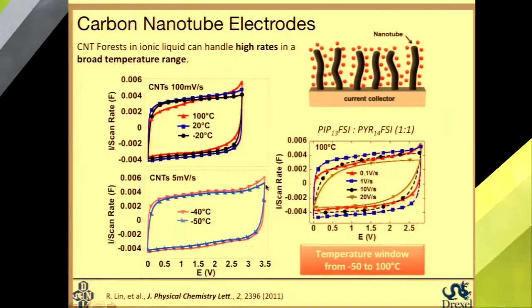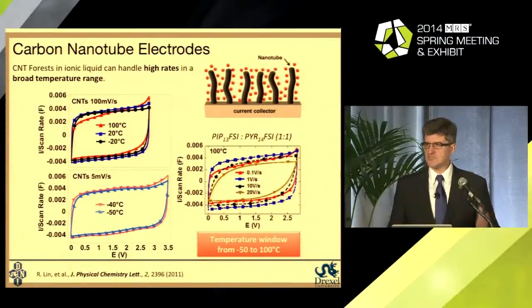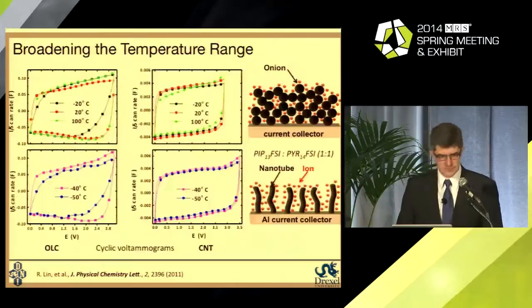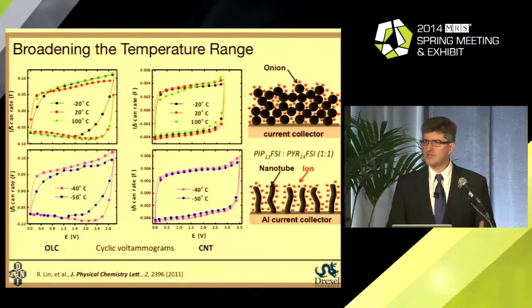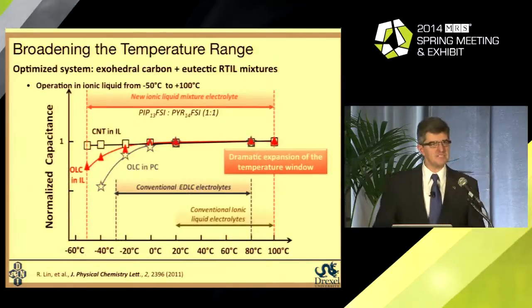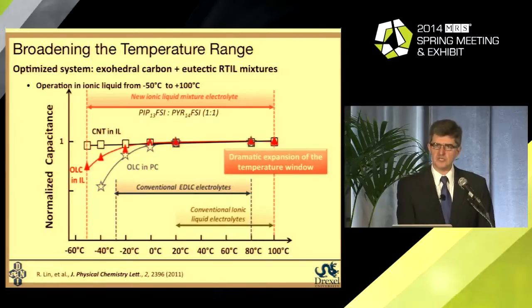But we still can charge it at -50 degrees C, keeping the same nice rectangular perfect capacitive performance. So before this work, there was really no single paper showing that ionic liquid electrolyte can be used below room temperature at all. And here, simply by designing the carbon electrode, we can push it down to -50 degrees C. And you can do exactly the same thing on carbon onions or graphene electrodes. So as a result, by designing with carbon, by understanding how to match carbon electrode materials and electrolyte, we will be able to expand the temperature range from -50 to 100 degrees C for electrical energy storage application. So if you have this as a battery in your car, you will be able to start your car in Alaskan winter or Arizona summer, and you will be able to operate it safely because ionic liquids are non-flammable and have very low vapor pressure.